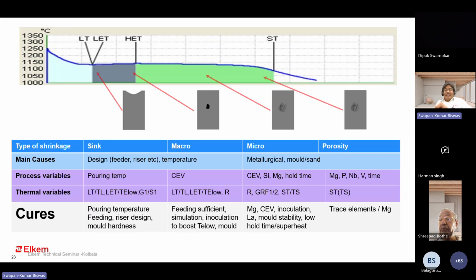So this is the thermal analysis graph. When you go through this, it will give you the idea. For micro shrinkage and porosity, the process-related factors are mostly carbon equivalent, silicon level, residual magnesium, which is most important, and holding time. In case of shrinkage porosity, then phosphorus, niobium, vanadium, and time. These elements are found in most cases to be overlooked. People mostly check the residual magnesium, carbon equivalent, silicon and some other elements. But these are most important to control the microporosity.